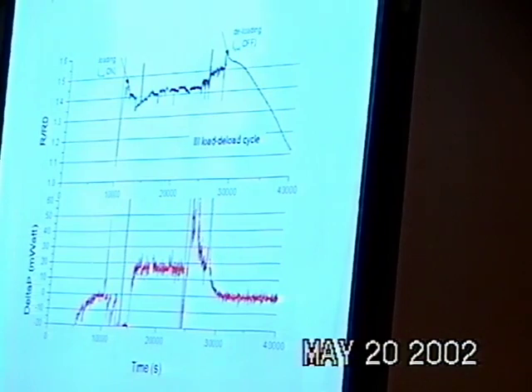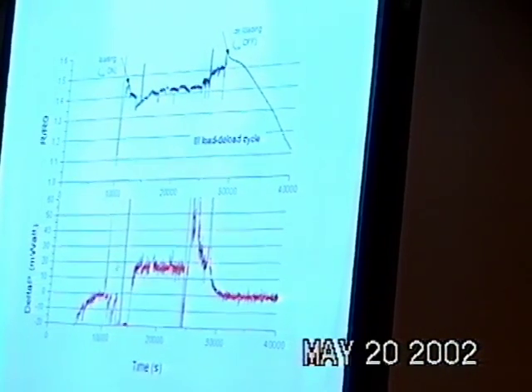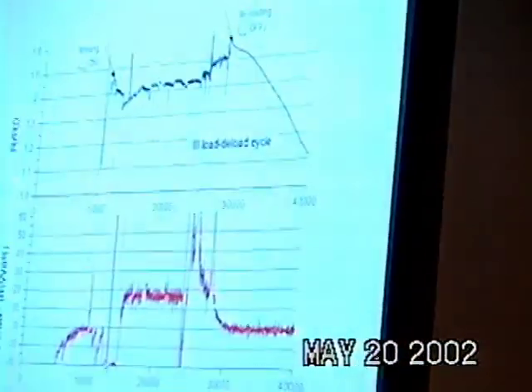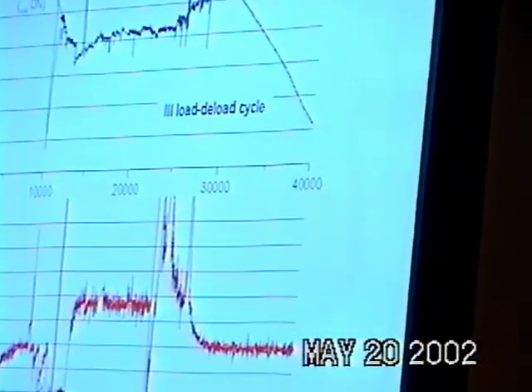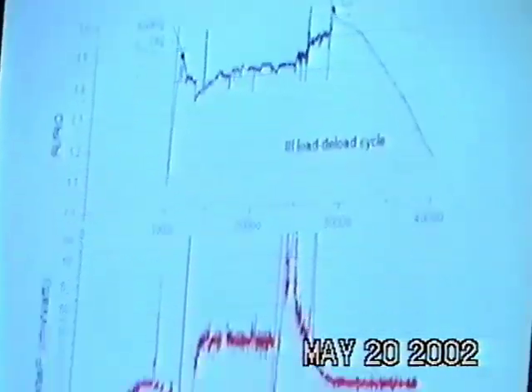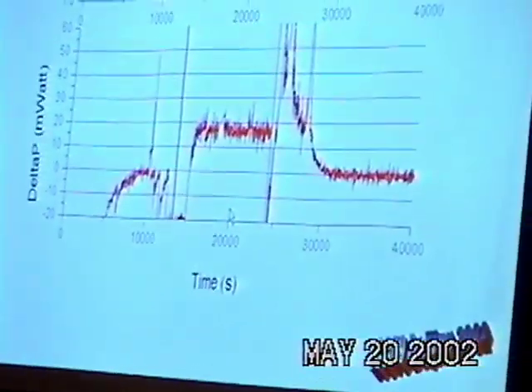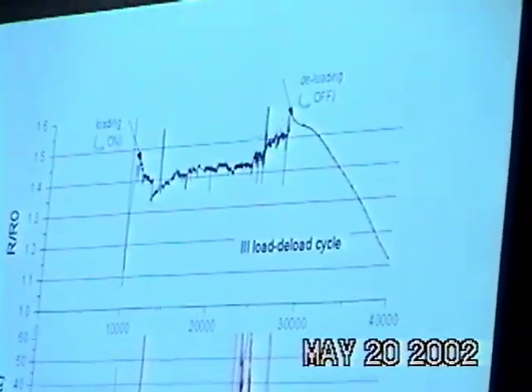And as soon as after the drop in the resistance, the increase in the loading, you can see the comparison of a delta power in a time that is the time constant of the calorimeter. In this case, you can see this is about 500, 600 seconds. The time constant of our calorimeter, the tau of our calorimeter, is 160 seconds. And this effect is fully reproducible. We obtained this kind of samples several times.